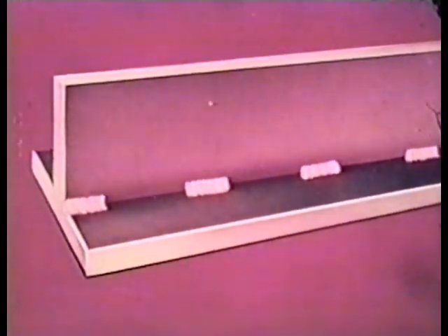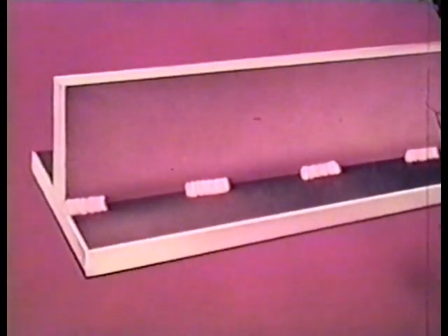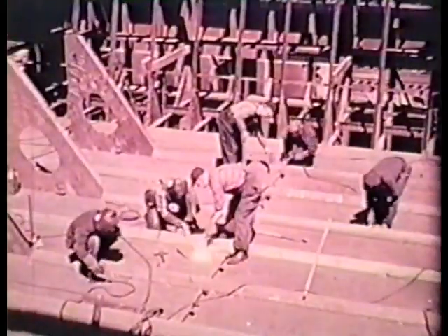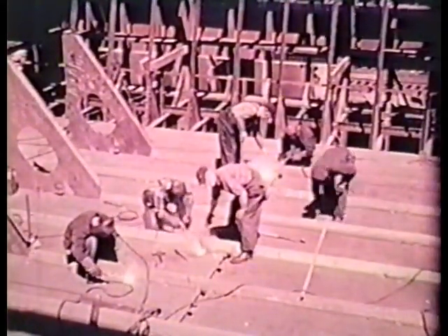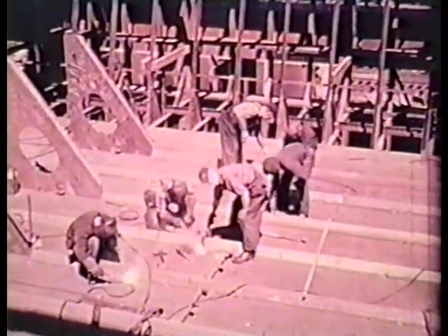Your own experience will uncover other methods. For example, intermittent welds frequently give all the strength required. In this way, you can use 2/3 less weld metal and reduce the effective shrinkage force by that much. On this bulkhead, good engineering design permitted the use of intermittent welds, which meet all strength requirements and at the same time minimize distortion.